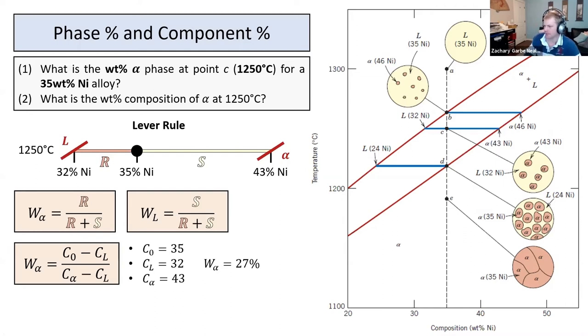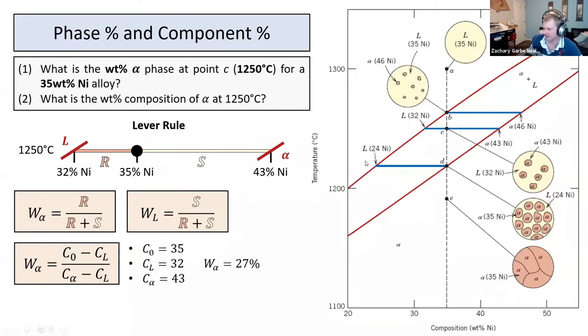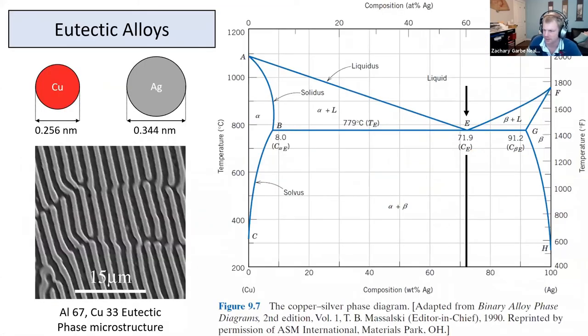There are kinetic limitations as well. If you cool quickly, you'd have an alpha precipitate at a higher percentage — say 46% — and the next layer would have less and less nickel because it takes time for atoms to diffuse. At higher temperatures kinetics are faster, but the thermodynamic driving forces are lower. We'll look at that a little later with steel.